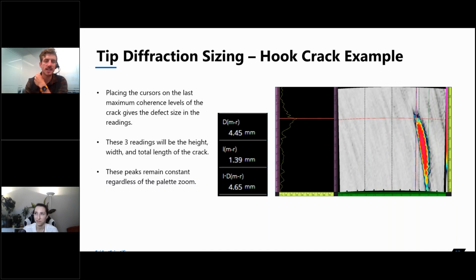Another example, we're coming back to the same hook crack that Emily was talking about earlier. So in order to size this crack, all we have to do is place our data cursor on the last hotspot in our defect, and then using the A-scan, we find the peak, very similar to what we do in TOFD, but now this is a rectified A-scan rather than the absolute A-scan. And by placing a reference cursor on the tip of our defect, using the readings, we automatically know that from my reference cursor to my measurement cursor, which is placed at my depth, this crack is 4.5 millimeters high, which is super easy. When we remember our TFM image from earlier, the crack was separated in two portions. So sizing this defect using PCI is going to be significantly easier and significantly faster than with TFM.